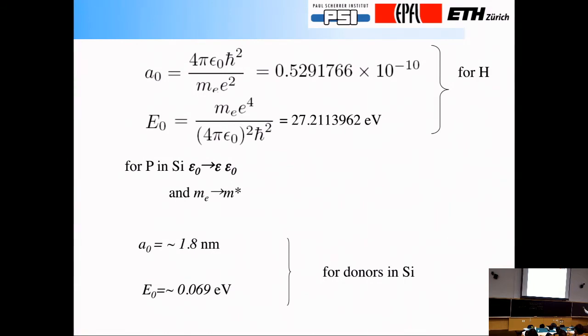Not half an angstrom, but 1.8 nanometers in radius. But at the same time, of course, it's more weakly bound. The binding energy scales like the effective mass divided by the dielectric constant squared. And so my Rydberg, which is tens of eV, now is 70 millivolts. So basically, the physics just goes through in the same way as for ordinary vacuum.